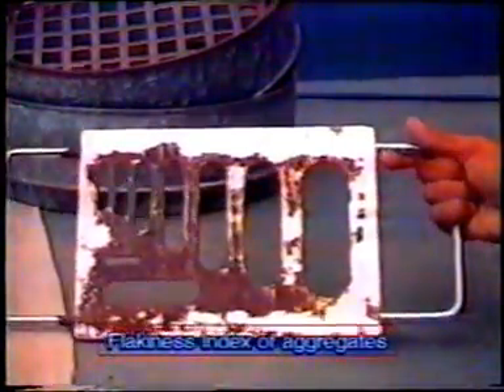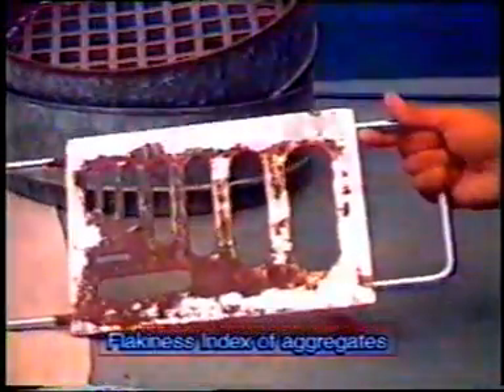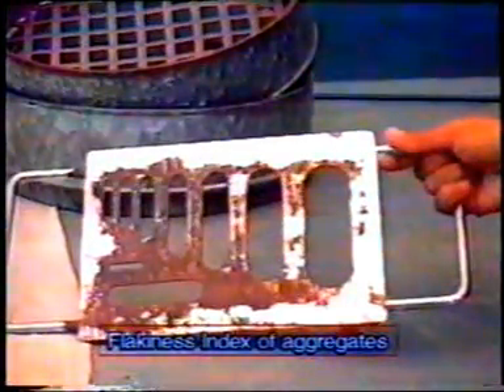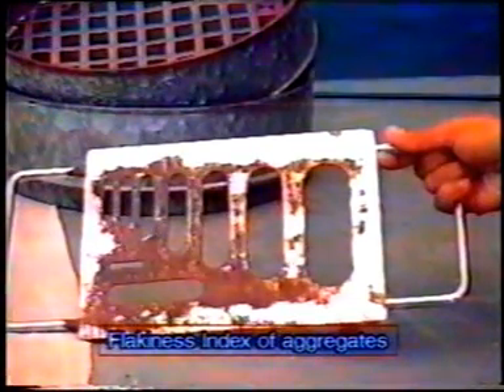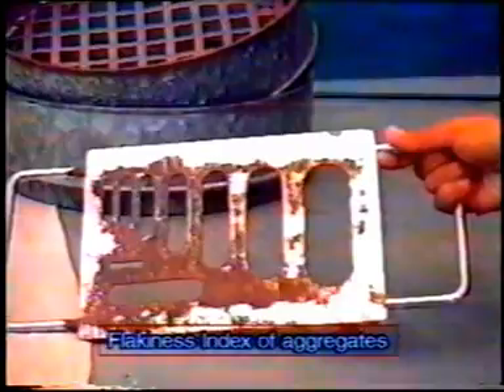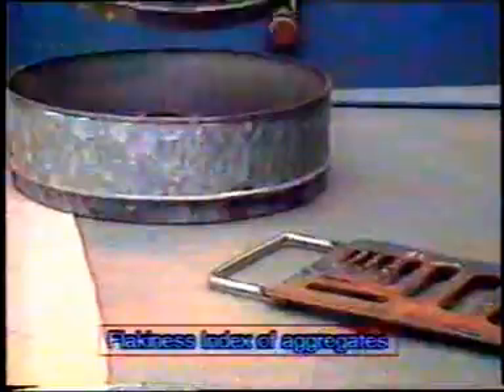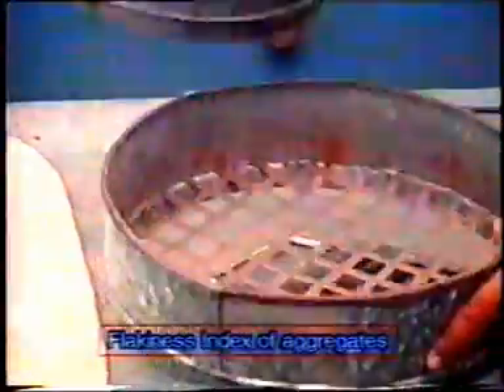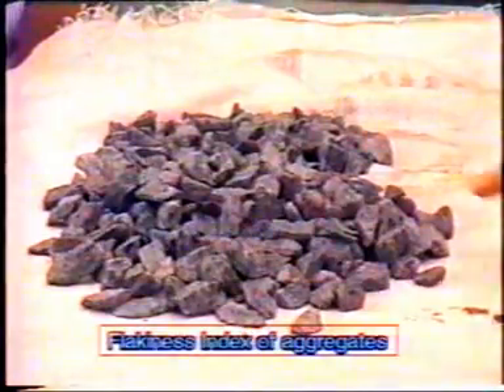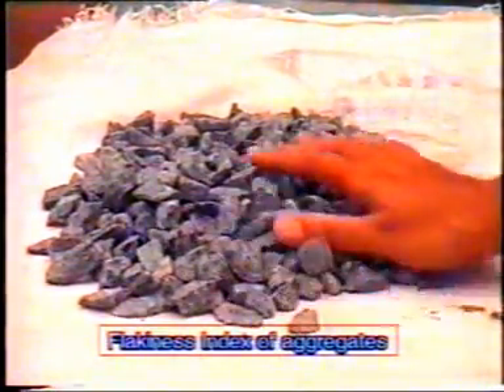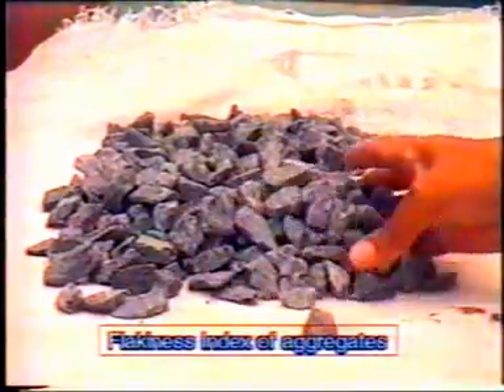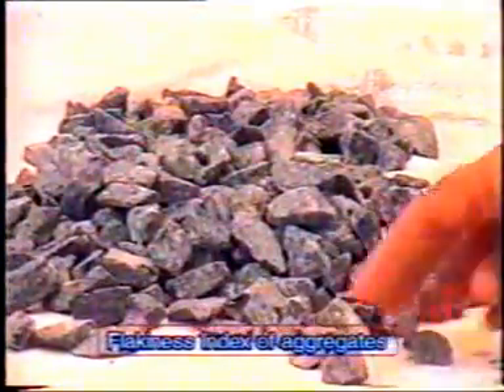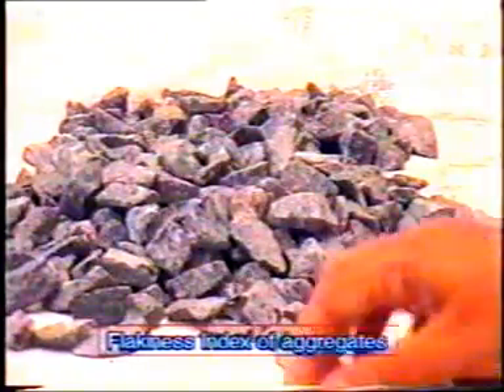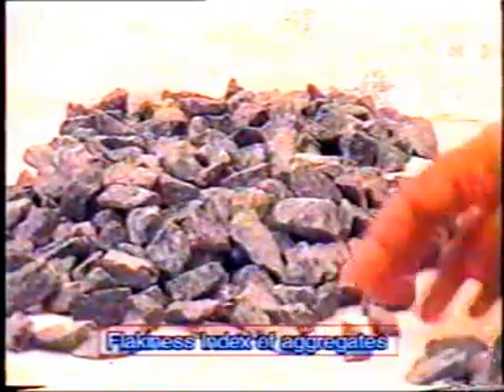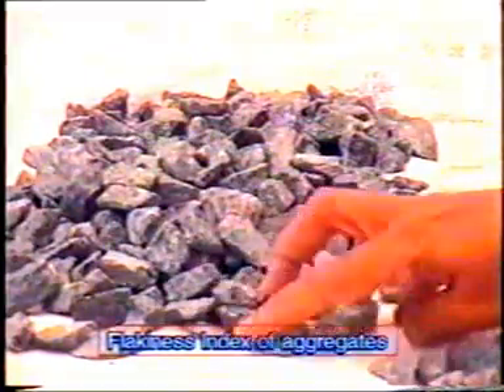Now let us see the apparatus required for the flakiness index of the aggregate. Number 1, thickness gauge. This is as per IS 2386 part 1 of 1963. Balance and the IS sieves are the same as those of the elongation index. Now let us see the procedure of determination of flakiness index of aggregates. A fraction of aggregate sample that passes through the 20 mm sieve and is retained on the 16 mm sieve is taken. 200 pieces of such aggregate are selected from the sample.